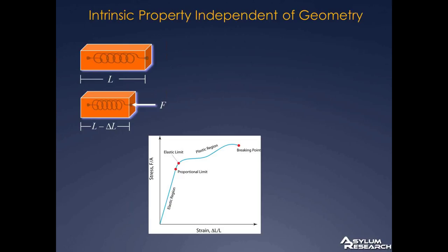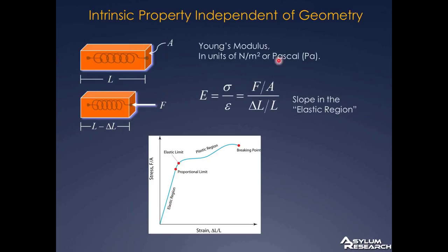So Young defined the stress, which is F over A, where A is the area over which the force is applied, and gave it the Greek letter sigma. If you divide that by the strain, epsilon, which is the change in length along the direction of the force divided by the starting length, those two are connected by this thing called Young's modulus, the E. Here it is on the same graph, with the axes changed to stress and strain. Young's modulus is the slope along that elastic region.